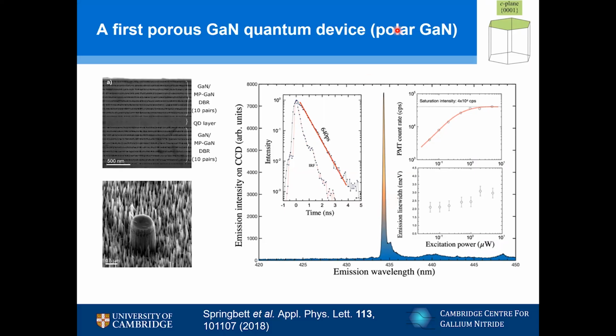I have a follow-up question. How do you know that the material composition within the quantum dot is uniform? I'd assume it isn't, actually. Oh, so in the microscopy we can see there are compositional gradients within the quantum dot. In InGaN in general, because this is a highly piezoelectric material, and also because of the strength of the indium nitrogen bond versus the gallium nitrogen bond, which are very different, and the electronegativity of both, you find that we get very strong localization of the hole, even in quantum wells, on very small fluctuations of indium content.